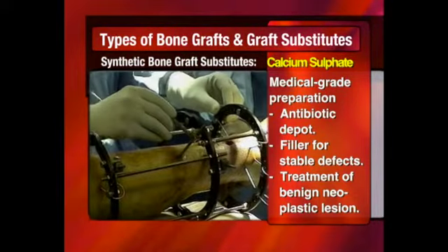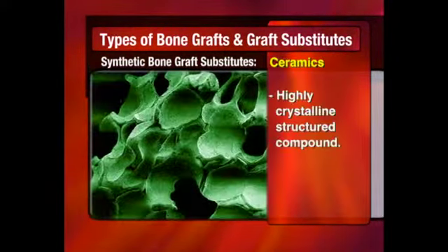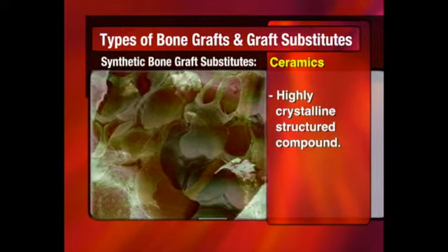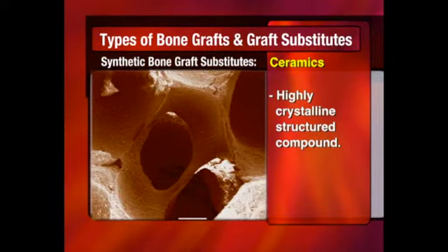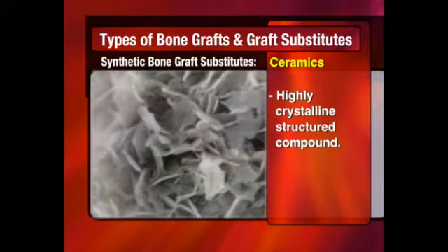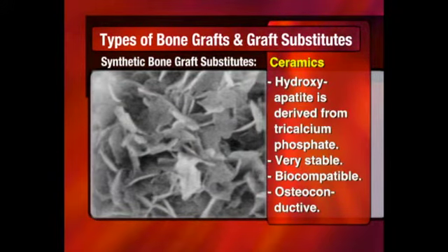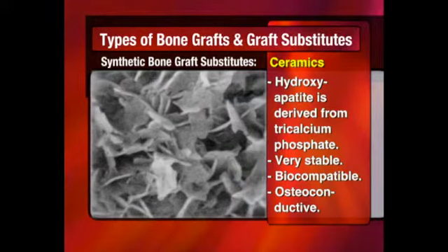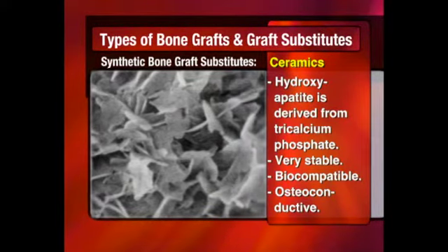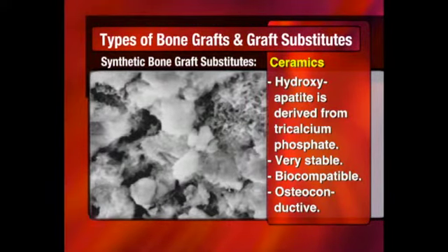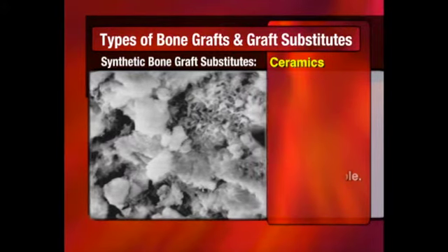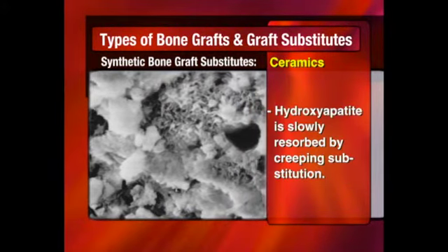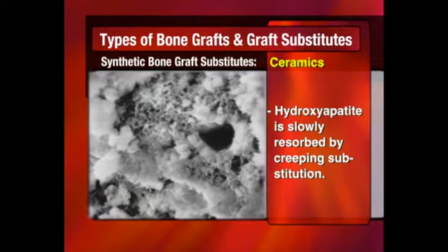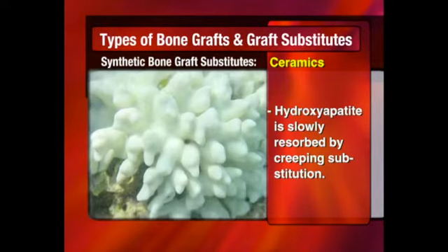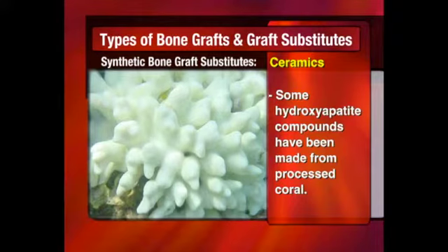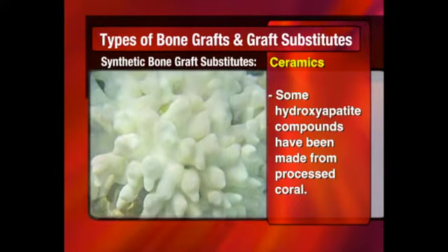Today, a medical-grade calcium sulfate preparation is available and is used clinically as an antibiotic depot and as a filler for stable bone defects, such as a metaphyseal defect following fracture, or for treatment of a benign neoplastic lesion, such as a bone cyst. Ceramics are a class of compounds with a highly crystalline structure made from the sintering of natural mineral salts. Hydroxyapatite is a ceramic derived from tricalcium phosphate and is a very stable biocompatible compound with excellent osteoconductive properties. Because of its highly crystalline form, it is very slowly resorbed by creeping substitution.